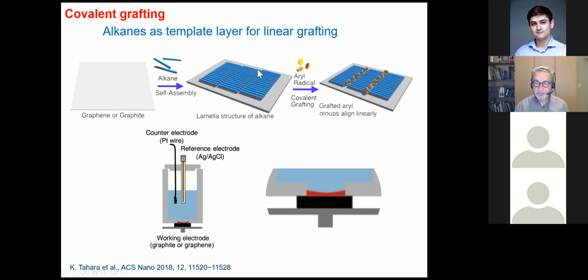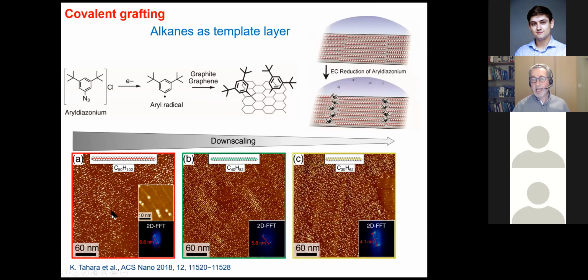This should be the most reactive area. And indeed, we succeeded in tuning the reaction conditions in a way that the radicals attacked the surface, but only in between rows of these alkane chains. And here you see STM images that support my claim, where we have used alkanes of different length. All these bright dots here are individual grafted molecules, and you can clearly see the row-type structure which is formed, and this is due to the templating effect of the alkanes.